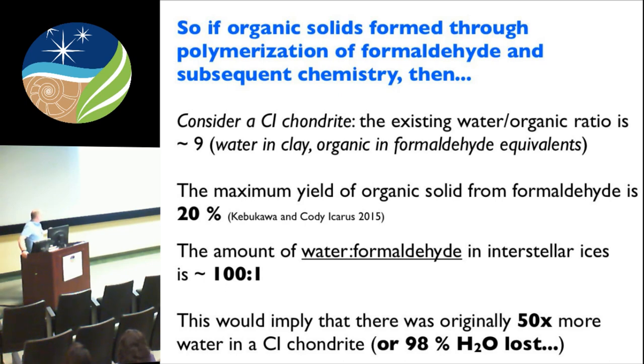So, if you look at interstellar ices, or for that matter, comets, as a signature of what interstellar ices might be, typically the ratio of water to formaldehyde is about 100 to 1. And so, when you apply that to a CI chondrite, you end up with the idea that there must have been 50 times more water in that chondrite than there currently is now. In other words, 98% of the water that was there is gone, and now you've got a rock. This actually makes perfect sense, because obviously you need more water than you've got if you're going to make a clay. Clays are made at the bottom of the ocean, so there's plenty of water there. So clearly there had to be much more water.